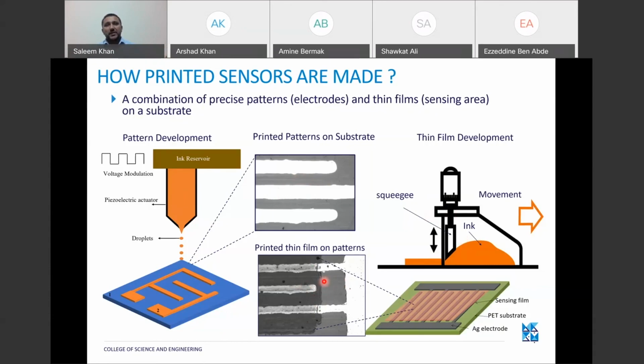Here in this case, you can see this one is deposited by a thin film applicator, and the thickness of the layer can be controlled by adjusting the standoffs in the system. So once we print these patterns using inkjet technology, they are sintered in an oven, and then they are placed in such a way as to avoid interconnections or deposition on the contact pads. We just deposit the sensing layer on the respective area, on the interdigital electrodes. So this is how the printing works.